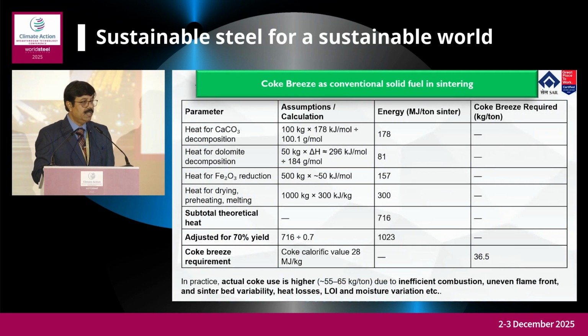This is the heat value we have calculated, including the heat of calcium carbonate, which the coke breeze utilizes for heating the iron ore fines mixed with flux. Flux means, in order to maintain the basicity in the blast furnace, we use crushed lime of -3 mm size and dolomite mixed into the iron ore fines to form a raw mix. The heat of the coke breeze is utilized for heating the iron ore fines in pure form, as well as the flux fines in the form of lime. So this heat is imparted to calcium carbonate and dolomite, and then used for reduction of the different forms of iron oxide.